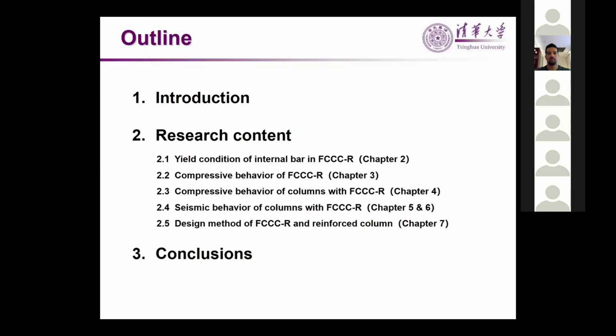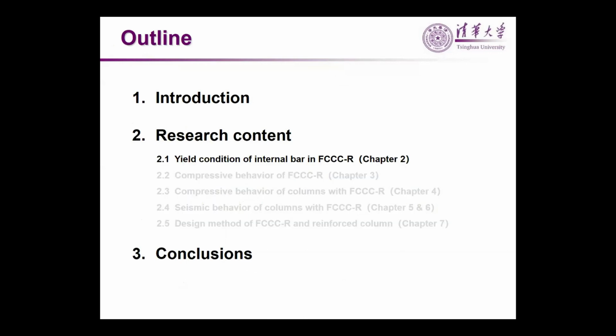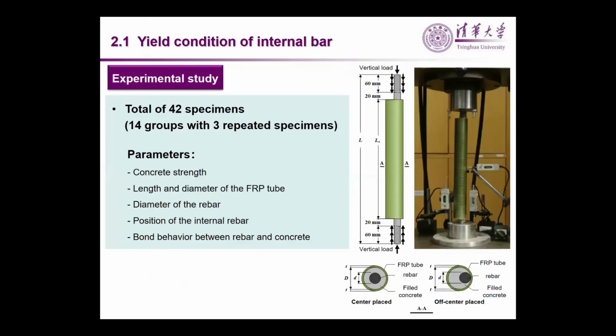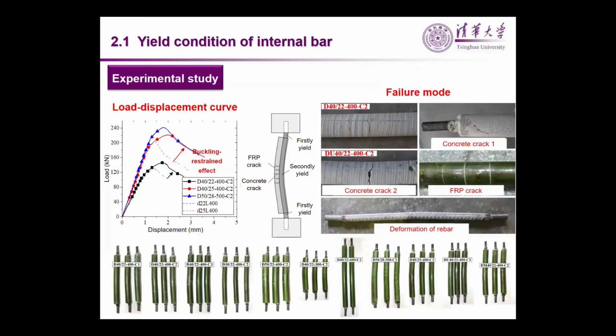And in chapter 2, the yield condition of the internal steel bars under compression is firstly studied. And an experimental study on 42 specimens under compression was carried out. The axial load was applied only on the internal bars in order to figure out the buckling resistive effect of the FCCR. And according to the test results, all the specimens illustrate a quite similar failure progress. The peak load can reach or even exceed its yield strength for bars with a relatively large slenderness under axial compression.